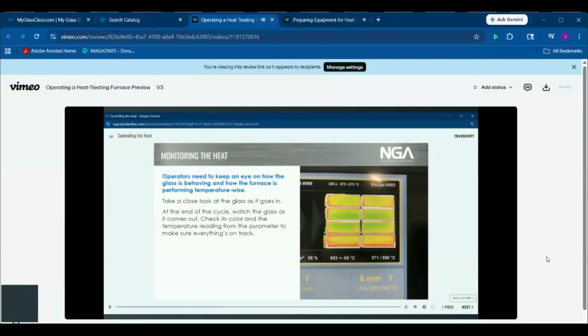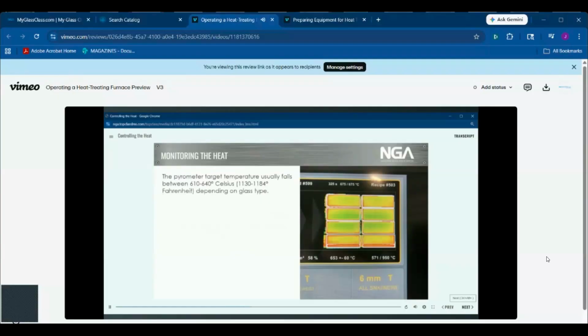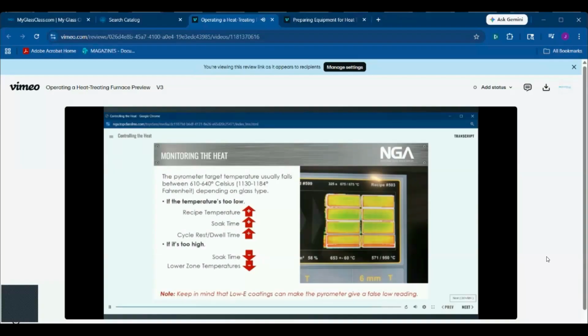Check its color and the temperature reading from the pyrometer, which is the furnace thermometer, to make sure everything's on track. The pyrometer target temperature usually falls between 610 to 640 degrees Celsius, depending on glass type. If the temperature's too low, the glass might break during quenching because it's underheated. In that case, try bumping up the recipe temperature, soak time, or the cycle rest dwell time. If it's too high, the glass can get distorted or show issues like roller wave distortion or pitting. Then you'll want to cut back on soak time or lower the zone temperatures. Note, keep in mind that low E coatings can make the pyrometer give a false low reading.